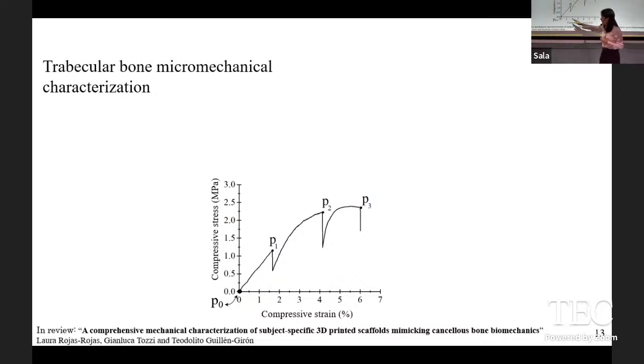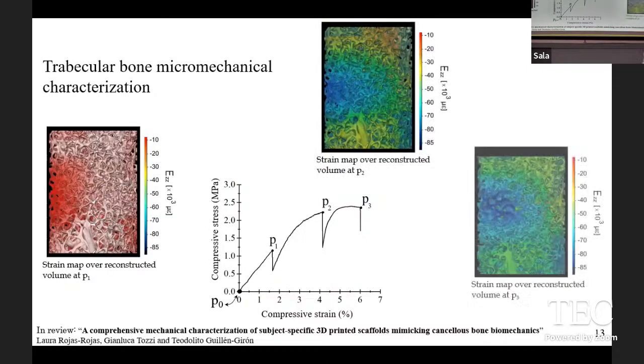We had to take images at certain time points. So we began without any compression, then one in the elastic section, one near the yield strength, and one near the ultimate compressive stress. And doing this procedure that I just previously explained with DVC, we were able to obtain the strain map distribution over the reconstructed volume for the bone.